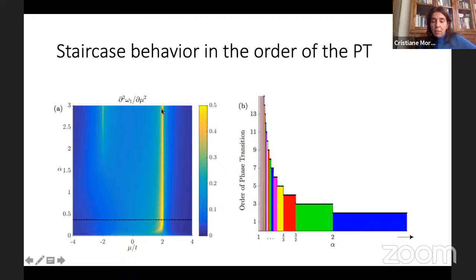So before I had a phase transition for alpha equal infinity between -2 and 2. Here was my topological phase, and here I had a trivial phase. So I see now that for the entire regime of alpha, the phase transition at 2 is well defined. But the phase transition at -2 is stopping. What I'm plotting here is the second derivative of the bulk. So it's a second order phase transition in the entire regime, and here it's stopping, okay?